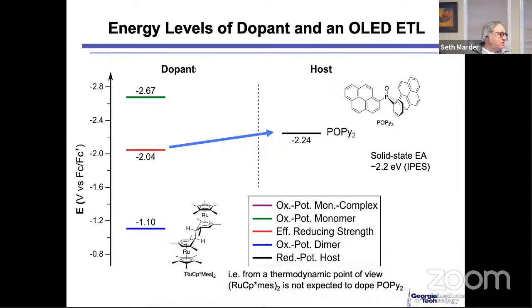It's just way too high. It's going to be thermodynamically problematic if you just think about it as a redox reaction, but it's not a redox reaction, because we know that once we oxidize this guy, it falls apart. But kinetically, it's not going to happen. Now, if we cleave this to make the 19 electron compound, that would have a reduction potential of negative 2.67, which gives us a little over 0.4 volts of driving force to actually reduce this. But the problem is we don't have that, and the thermodynamic reduction potential of this material is not that of either this or that, because the thermodynamic process involves cleaving this bond to give you that, and then that could transfer an electron.